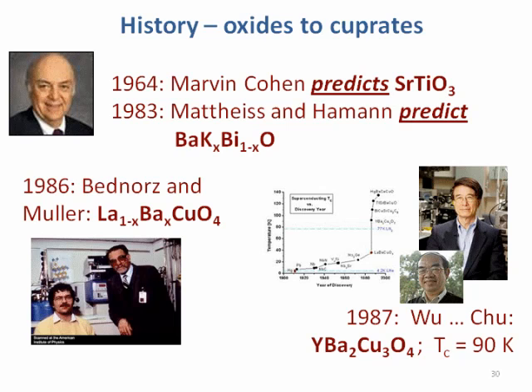Then, Paul Chu and Wu actually were the ones that, this was a plot of Tc versus time, and these are the cuprate superconductors. This is lanthanum barium copper oxide, and then these guys pushed it above the liquid nitrogen temperature. Okay, and they switched things around. It was a prediction. I could list a few other of these hits where people claim they predicted. My problem with saying that it wasn't serendipitous is these are really brilliant people, okay? And they work on this hard, full-time, studying, trying things. And they each have one hit, okay? So if any of these guys came up with a second superconductor, I would be more inclined to believe that they were predictive discoveries. So I argue that it's still serendipitous discovery.